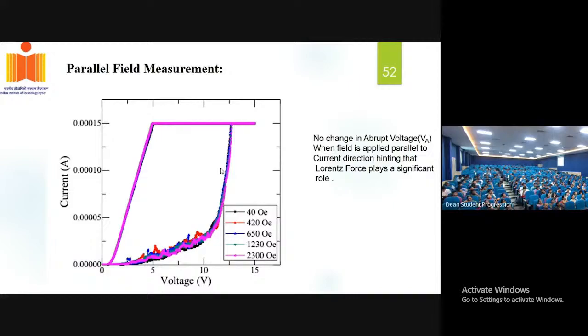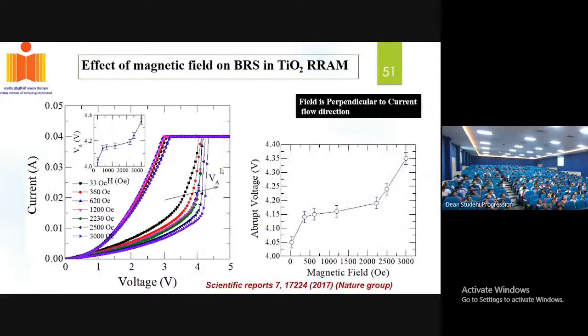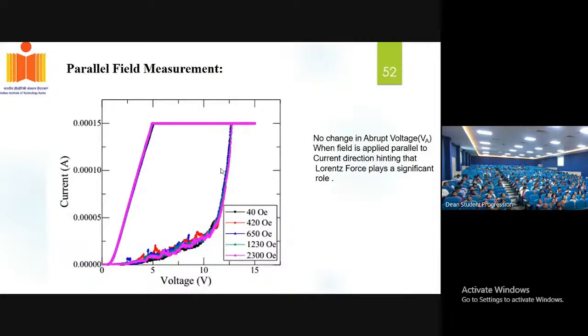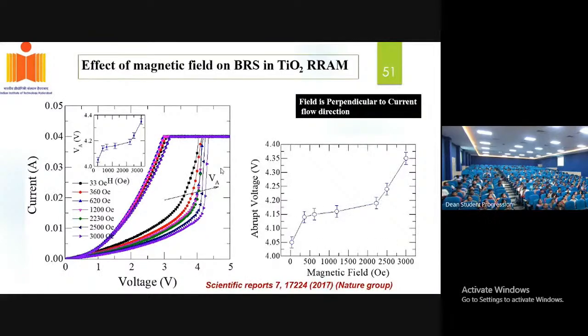We also applied the magnetic field in the parallel direction. That means that the electric and magnetic field both are in parallel direction. The Lorentz force should not come into picture. We should not see any significant shift of the set voltages when applying the magnetic field. So to our surprise, to prove our concept, we also got there is no shift for the set switching voltages with the application of the magnetic field when both the electric and magnetic fields are parallel to each other. So this essentially proves that the Lorentz force is affecting the device characteristics.